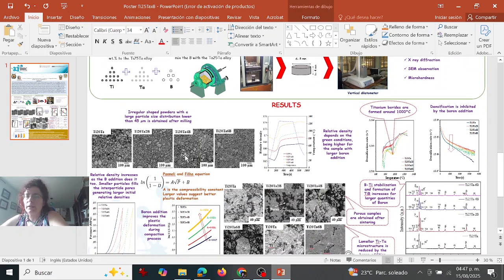First of all, we have in here some electron microscopy images. We have for the different samples in here, for example, we have the titanium 20% of tantalum. In here we have titanium 20% tantalum with 2% of boron. In here we have titanium 20% of tantalum and 4% of boron. And in here is the image for the 6% of boron.